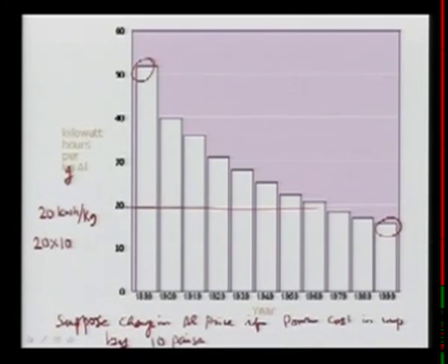So this is so many paisa, and then you want to find out for per ton. You multiply this one and divide by 100 because you want to get the rupees, and then you have 2000 rupees per ton of aluminum. I think we did it correctly. So just get a feel: if the rise in the cost of electricity is 10 paisa per unit, that may result in the cost of aluminum going up by about 2000 rupees per ton. That's a very, very significant amount.